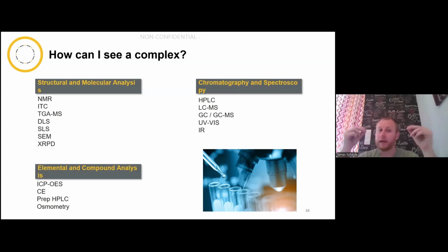because it would bind differently to the column. What happens in reality is, of course, that not all your actives are in a cyclodextrin cavity. So if your naked active peak is here, the fully complexed one is here, and you inject a solution that's a mix between the two, I mean that not all the actives are in the cyclodextrin complex, then you will see a peak in the middle.